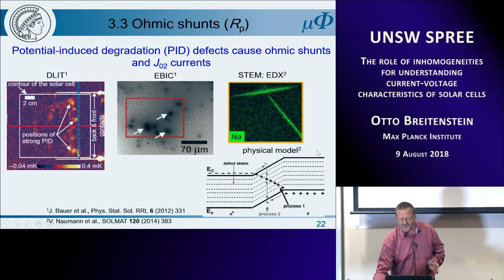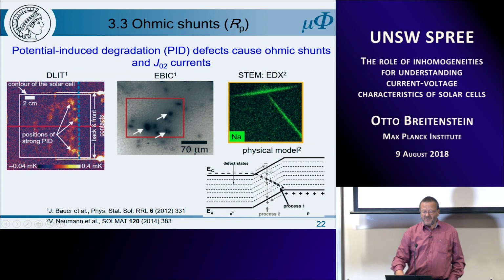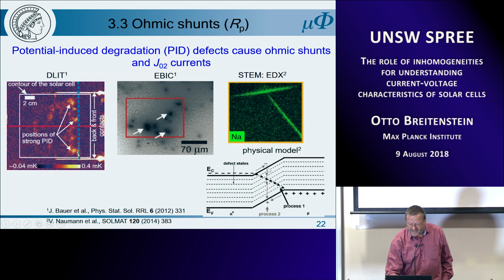And this is actually the physical model proposed by me, that the ohmic conductance is, as I have shown in the last slide, due to the hopping conduction, and the J02 is, as I have explained it before, for the J02 currents like this. So here we have both. At the beginning, when the defect density is still low, we have dominant J02 current, and then with stronger degradation, the ohmic shunting.